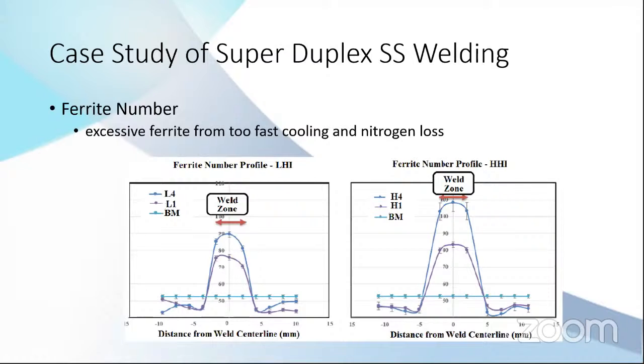In combination with nitrogen loss, you also have very fast cooling. This is autogenous weld, so very fast cooling creates a very high ferrite content in the weld zone. This is unwanted. It has very low corrosion resistance, it is very prone to cracking, and it has very low impact strength. The higher heat input has a very high ferrite content. The low heat input is also very high, which is also not acceptable, but still lower than the high heat input. The base metal is here. This is the first pass. This is the fourth pass. The more heat input you give, the more ferrite content you get, and it's not wanted because it's not balanced anymore.